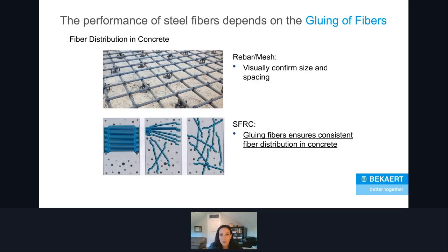And finally, the distribution. So I mentioned a few moments ago about the higher aspect ratio fibers tending to perform better. But what was also happening is that longer, thinner fibers, when they were introduced into the mix as loose, would also sometimes ball up. So Bekaert took this problem very seriously and did a lot of R&D to come up with a solution to address it. And what they did was they developed a gluing solution.